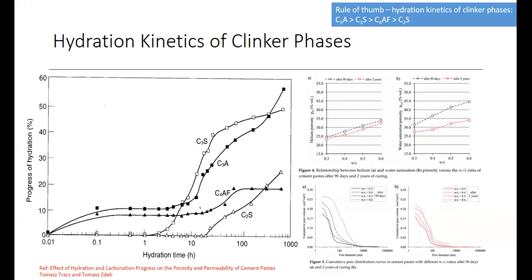Since those are exothermic reactions, they deliver more heat to the atmosphere. So we can identify how much heat could be generated by changing the chemical composition of a particular cement. If I want to reduce the heat of hydration, I have to reduce C3A and C3S. Similarly, if I want to increase the heat of hydration for a cold country or some other purpose, I have to increase C3A or C3S. So those are the basic chemical compositions, or chemical engineering, we can utilize to change application behaviors at the civil or end-user site.